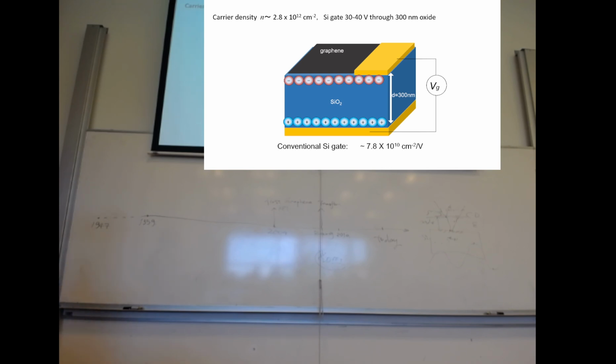So this induced carrier density, you can get with a 300 nanometer thickness of silicon oxide, whose dielectric constant is around 4, per volt. Every volt you put on the gate, you will obtain 7.8 times 10 to the 10 per centimeter squared carrier density. So that means before you break down this silicon oxide, you can have up to 10 to the 13th carrier density per centimeter squared. And that's how we usually do the experiment.